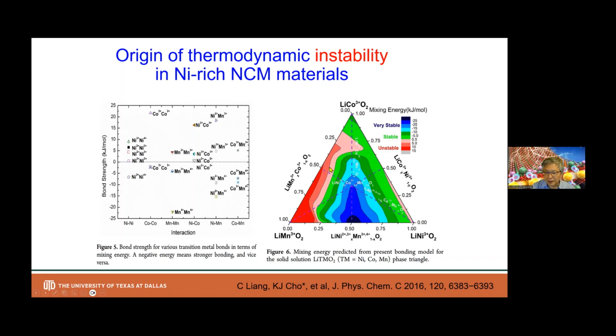So the cathode composition evolution over the last 3 decades was starting from lithium cobalt oxide, NCM111 is here, and then nickel-rich concentration is following this trend line. So most of them are stable, become less stable, and as we approach 75%, so 87% along this point, that becomes less stable. And this is assuming the so-called solid solution model. We'll go through that: what is the limitation of such a model, why this becomes an issue from an experimental point of view, and how we do the theoretical analysis to understand.